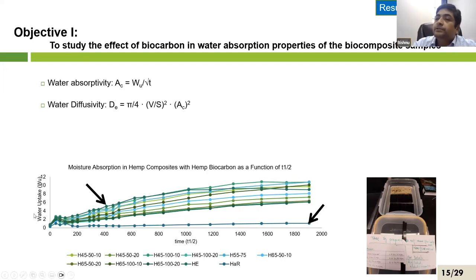Yeah, so here, the water uptake, basically, this would be the hemp. I think HAR is the hemp reinforced with the resin without the addition of the biochar in there, or it will be just the resin without any hemp. And then after that, the others are different formulations of the hemp. So we definitely saw that by adding the biochar we can reduce the amount of moisture uptake by the composite, and we can also slow down the rate of moisture absorption as well.